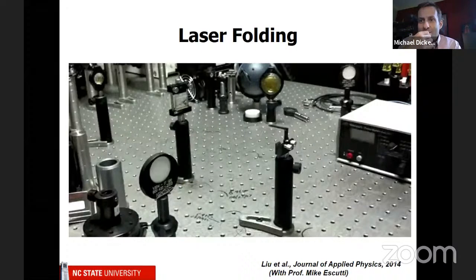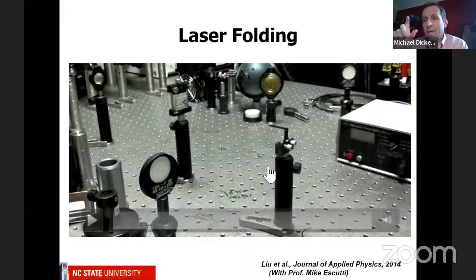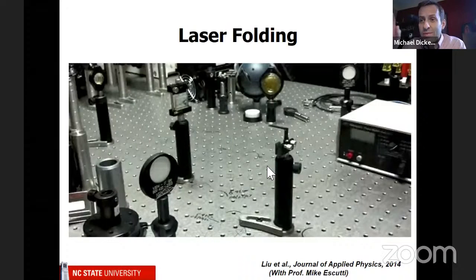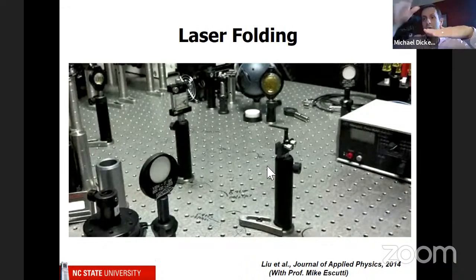Now, one of the things that I've been interested in, and we haven't really pursued, is whether, because lasers can be focused down into a small area, you might be able to scale this down. Right now, the materials that we're using are on the length scales of centimeters, or maybe as small as millimeters, but pretty big and relatively thick. So it would be interesting to try to make the hinges smaller. The tricky thing is when you make things really thin, you still need to generate a thermal gradient through your material. If you shine the laser here, for this to work, at least by this mechanism, you need the top part to get hot and the bottom part to stay cold or not as hot. And as you make these things thinner and thinner, it does not work quite as well.